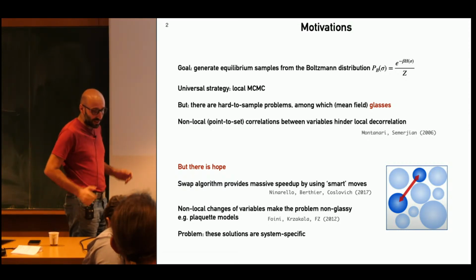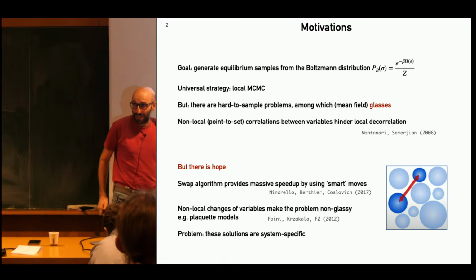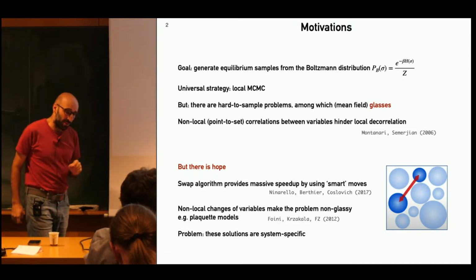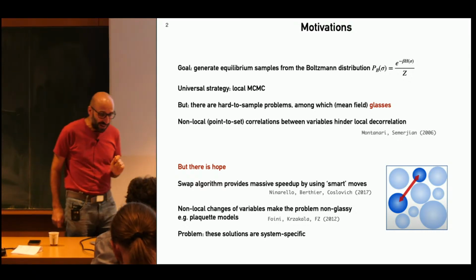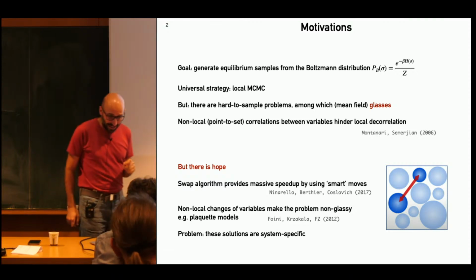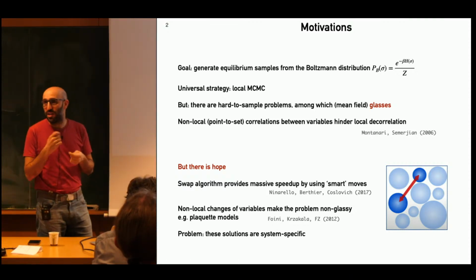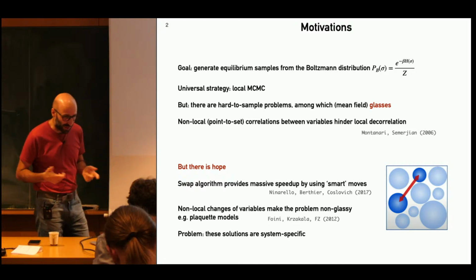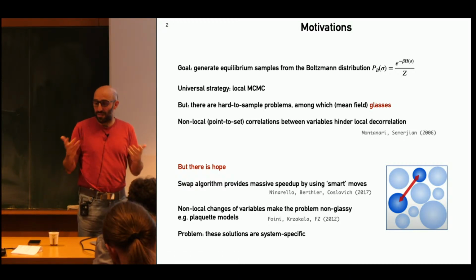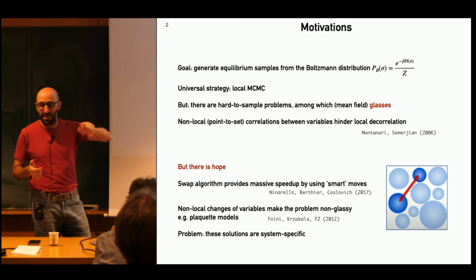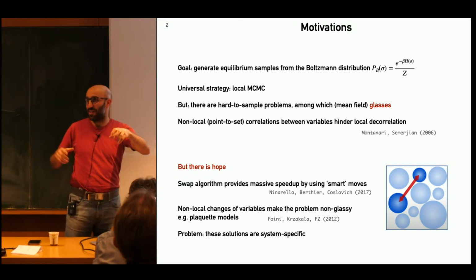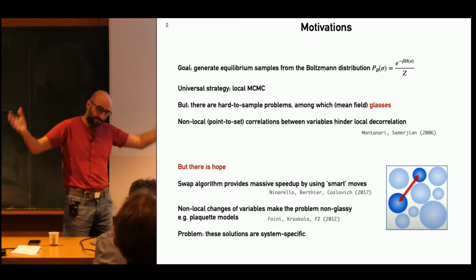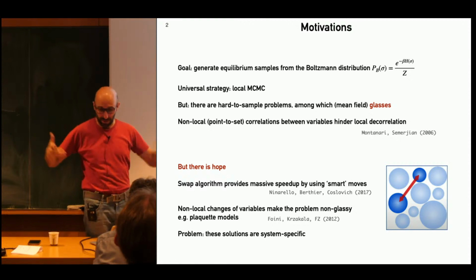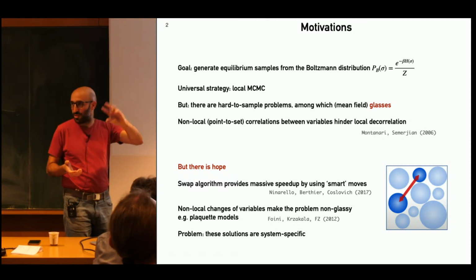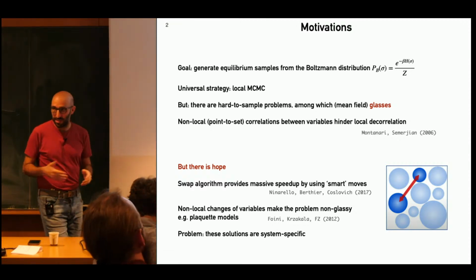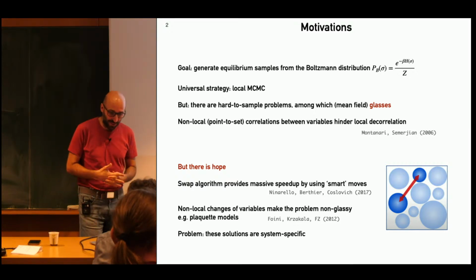In particular, there is a class of problems which are mean field glasses, for which you can prove, even rigorously, in that paper, that there are non-trivial correlations between variables. These are called point-to-set correlations that hinder local decorrelation. When you try to flip a spin or to move a particle, there is a strong correlation with the surrounding spins or particles that basically prevents your particle from moving. And that's why the local Monte Carlo fails.